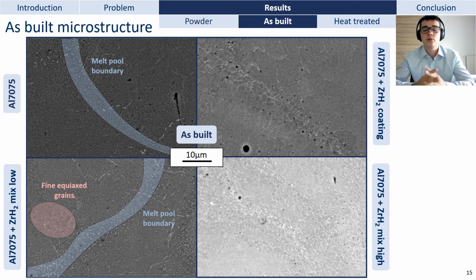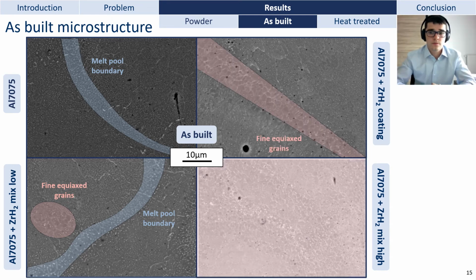These fine equiaxed regions are more present for the two other alloys, especially for the high zirconium content mix on these pictures. For all alloys, there are also some globular precipitates spread evenly inside the coarser grains.